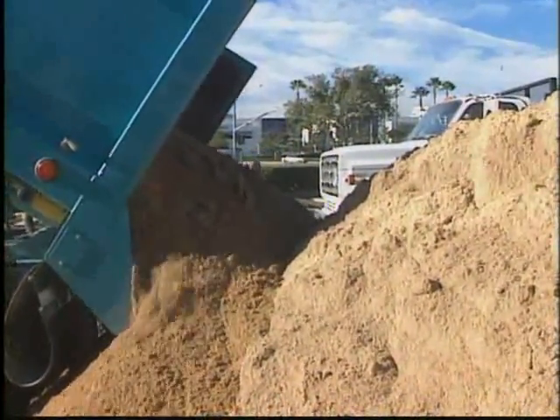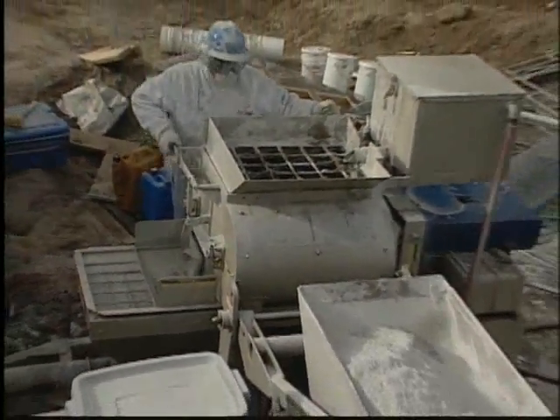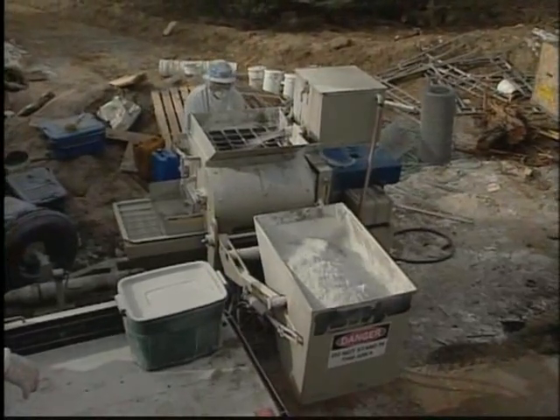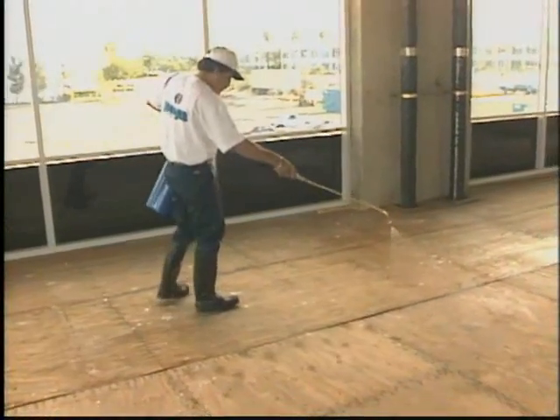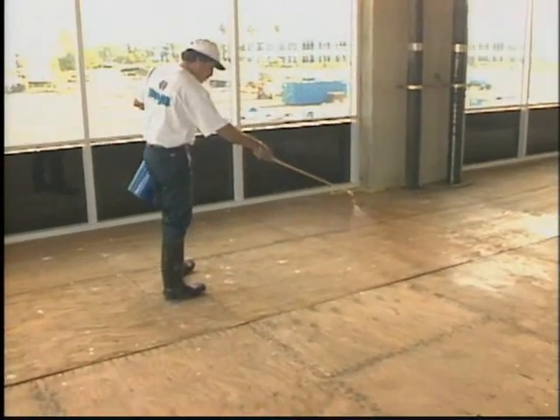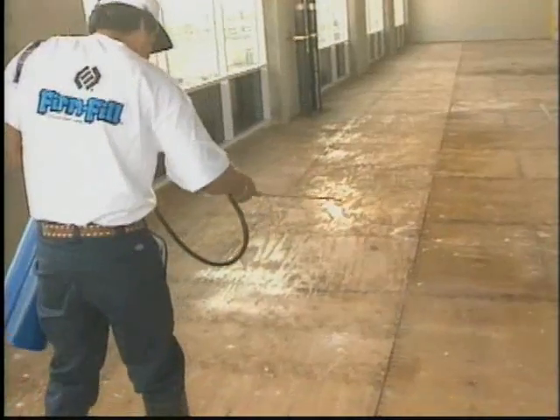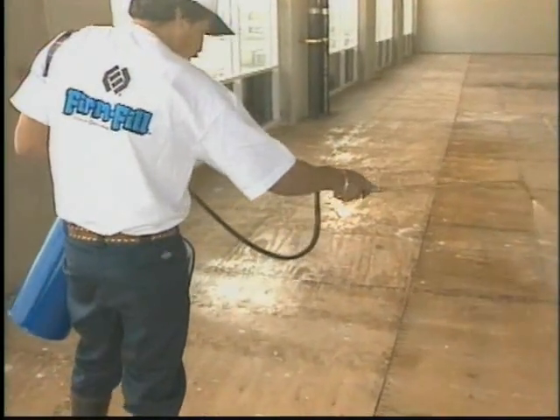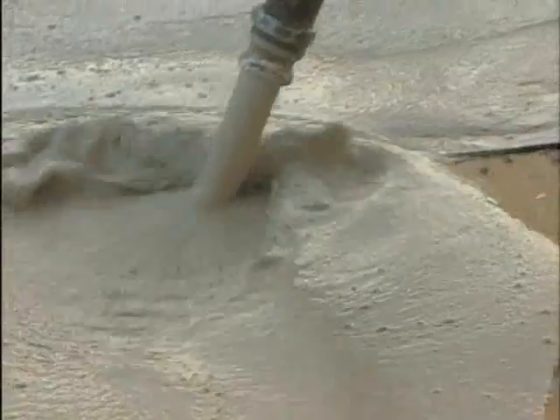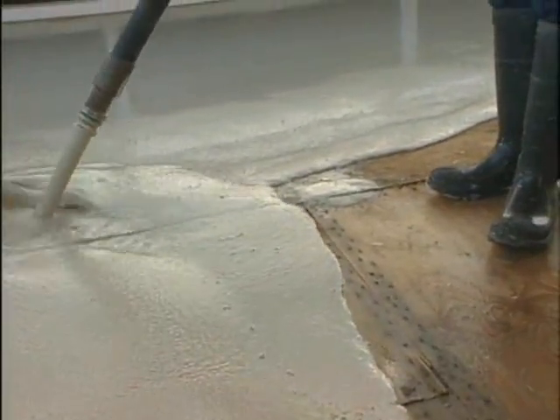Washed masonry or plaster sand is delivered to the project site on the day of installation, where it is mixed with Hacker Floor Underlayment and potable water to yield a lightweight, self-leveling slurry. Inside the structure, the subfloor is prepared to receive the Hacker Floor Underlayment. All surface cracks and voids are filled with a quick-setting taping compound. Then the entire surface is sprayed with Hacker Primer. Once the substrate is prepared, the Hacker Floor Underlayment is pumped in place over it.